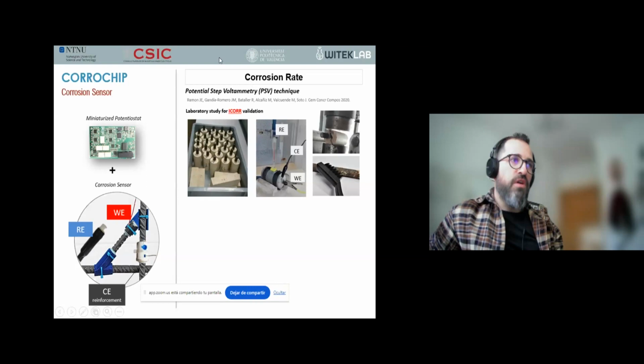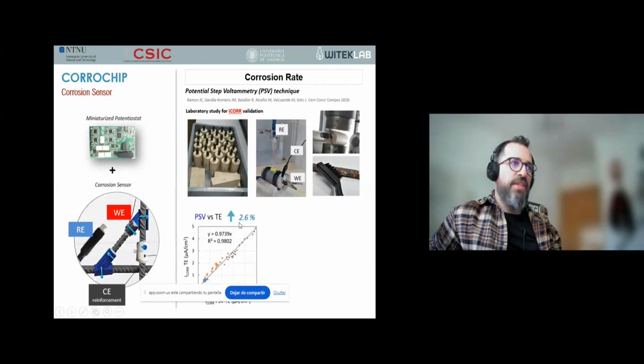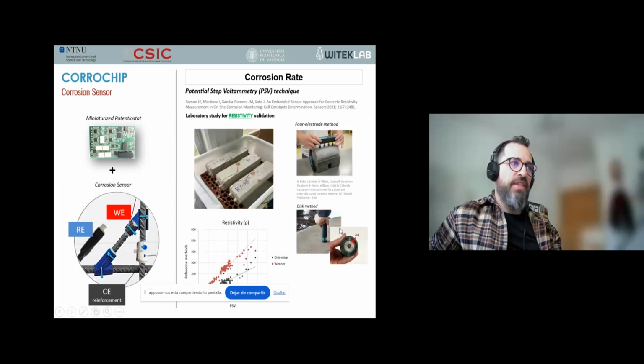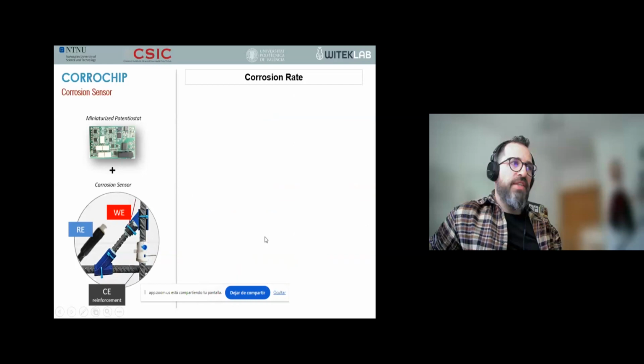Okay, here are some of the results obtained in these studies. For example, the validation of the corrosion rate obtained with PSV versus the reference methods, showing small dispersion with the Tafel method and also with the gravimetric method. And also resistivity was validated against reference methods, showing good correlation. So, therefore, the Corrochip sensor, in addition to corrosion rate, provides concrete resistivity.